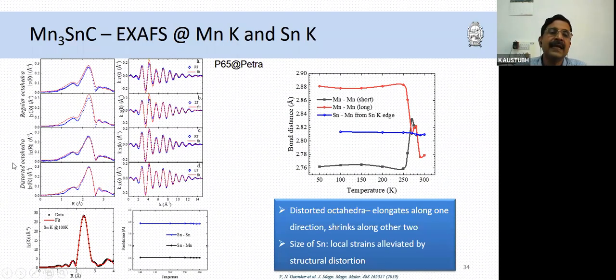And the experiments again were done at Petra, and these were fitted. So I have two models here, what I call a regular octahedra model, which is the cubic structure of Mn3SnC, and it fits the tin edge perfectly well without any problem, but it does not fit the manganese edge at all. It shows quite a discrepancy here. You can see that here. But if I distort the octahedra in the same way as I distort in the case of the gallium compound, I get a much better fitting.